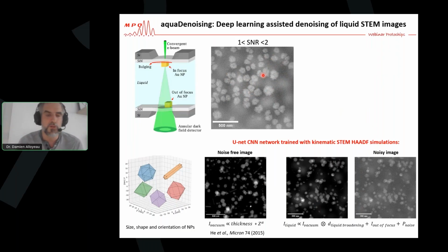If you ask a kid to draw around those nanoparticles, he'll be able to do it because you can see it. But if you ask a computer to binarize this image, it's actually a nightmare because the noise is very high. Here the signal to noise ratio of those particles is between 1 and 2. And you also have a very inhomogeneous background because you have a lot of particles that grow on the outer membrane, so they are highly out of focus, and they contribute to this inhomogeneous noise. So if you want to improve the signal to noise ratio and be able to treat this type of image automatically, you need to work on a deep learning approach, and that's what we did.